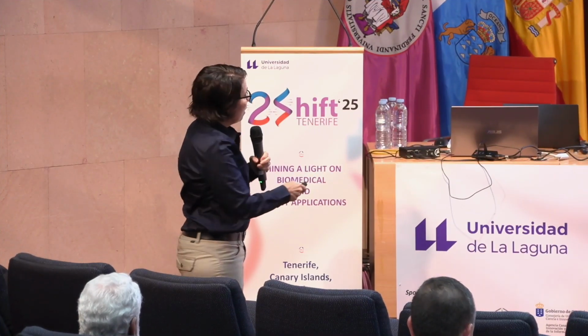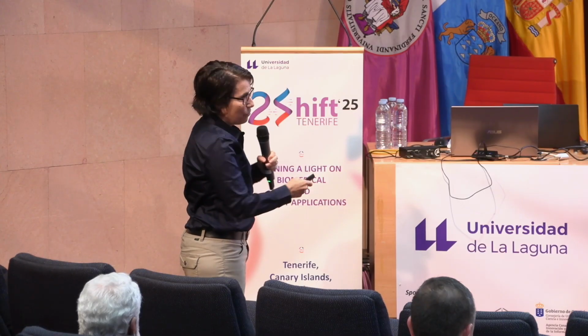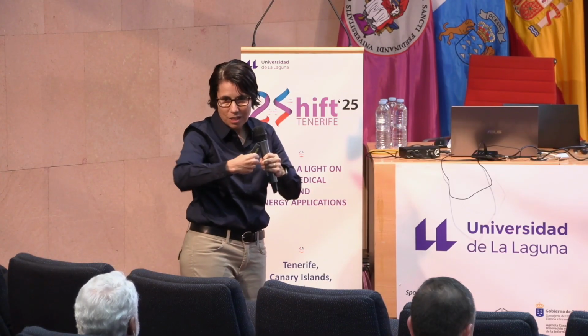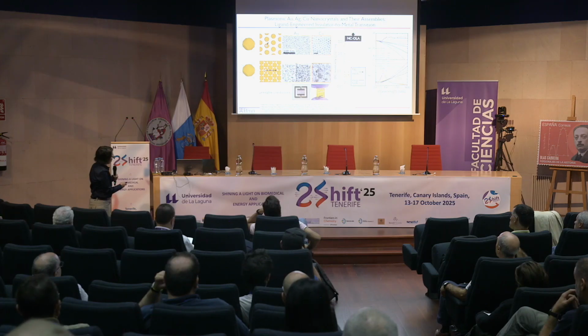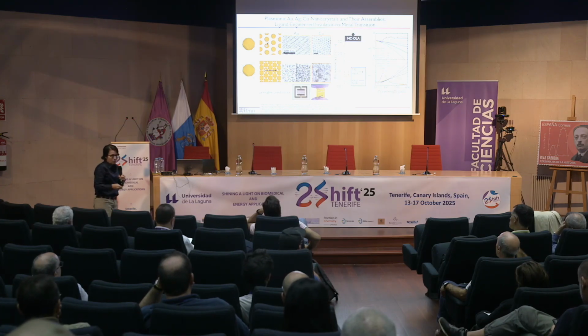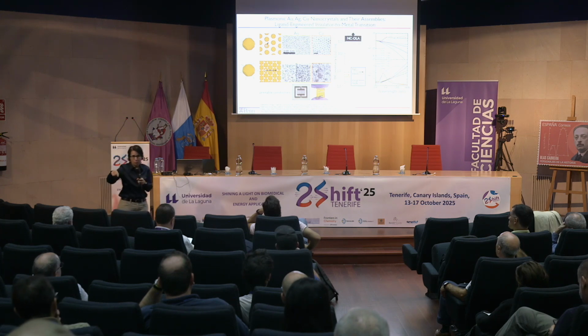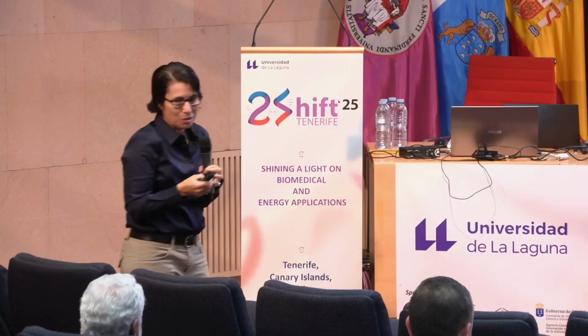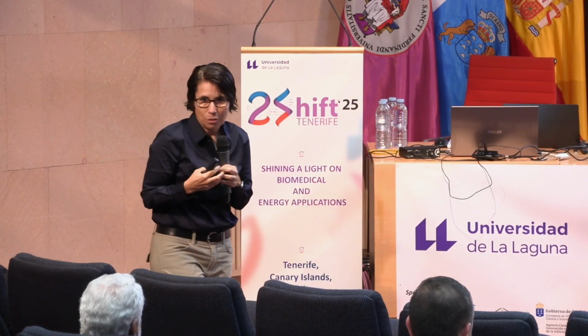And so you can see in the case of gold, in order to look in the electron microscope, we make a monolayer. And when these come together, obviously you get void spaces where the lost ligand volume comes from, but you can see that the nanocrystals start to fuse together. If you look at it in a multi-layer film, it looks like a gold film with lots of holes in it, empty spaces. You'll see in a moment we like to call these diluted metals because there are fewer atoms to contribute electrons to the